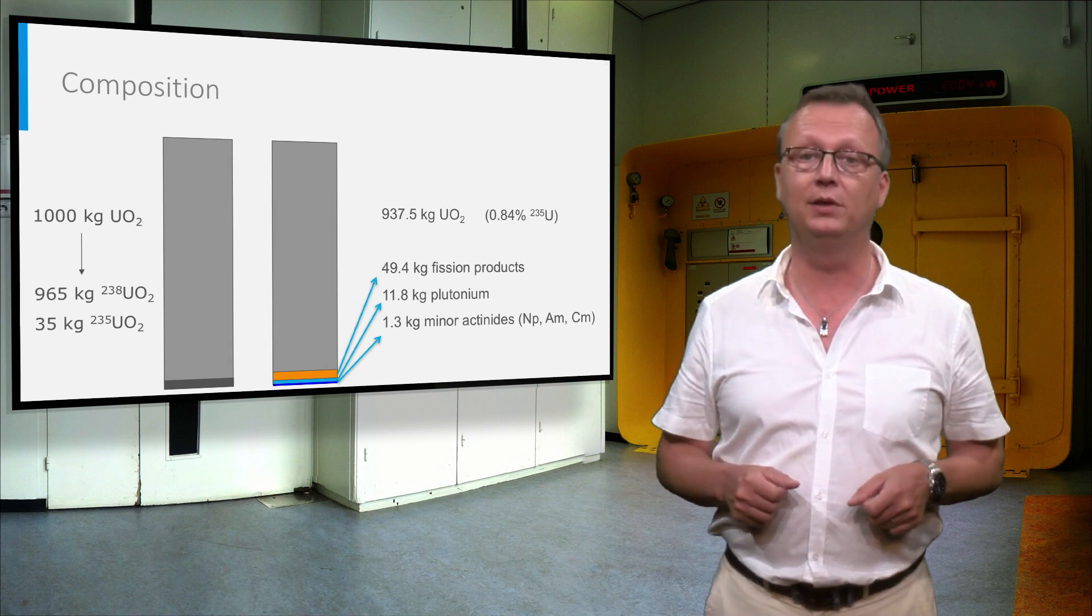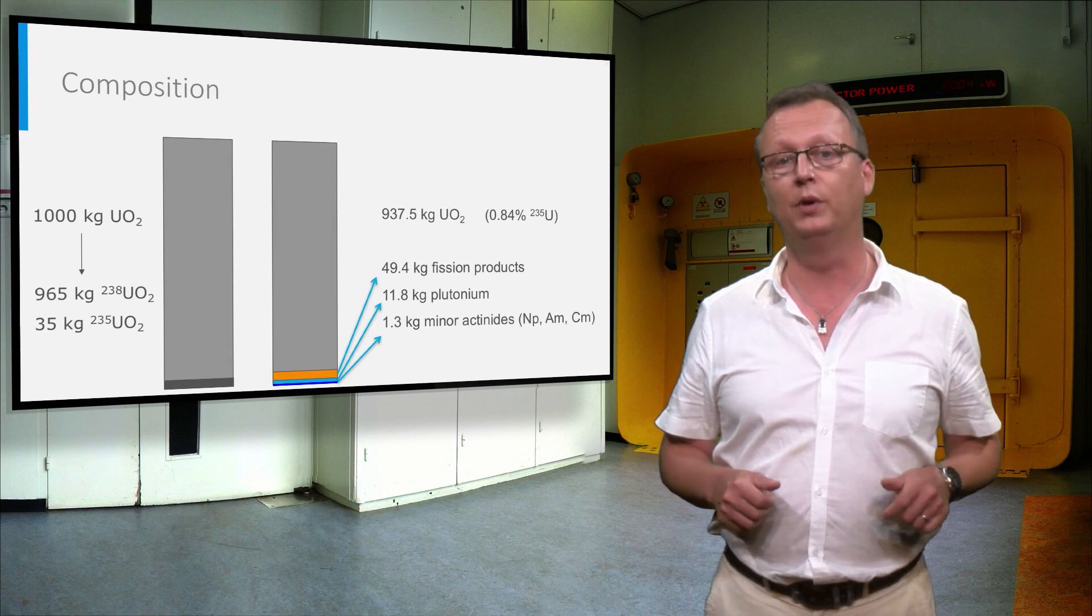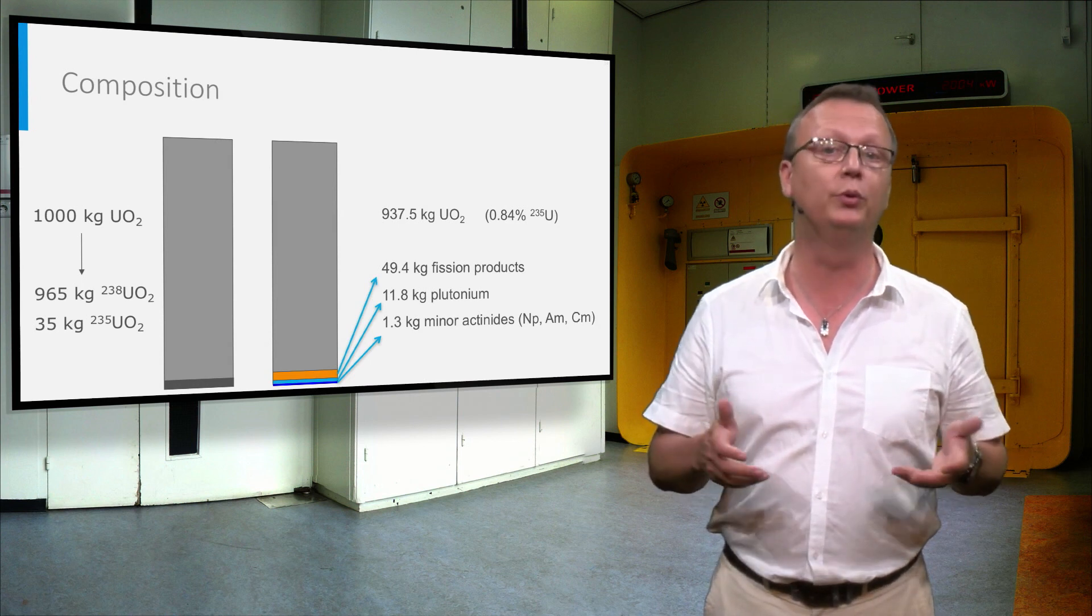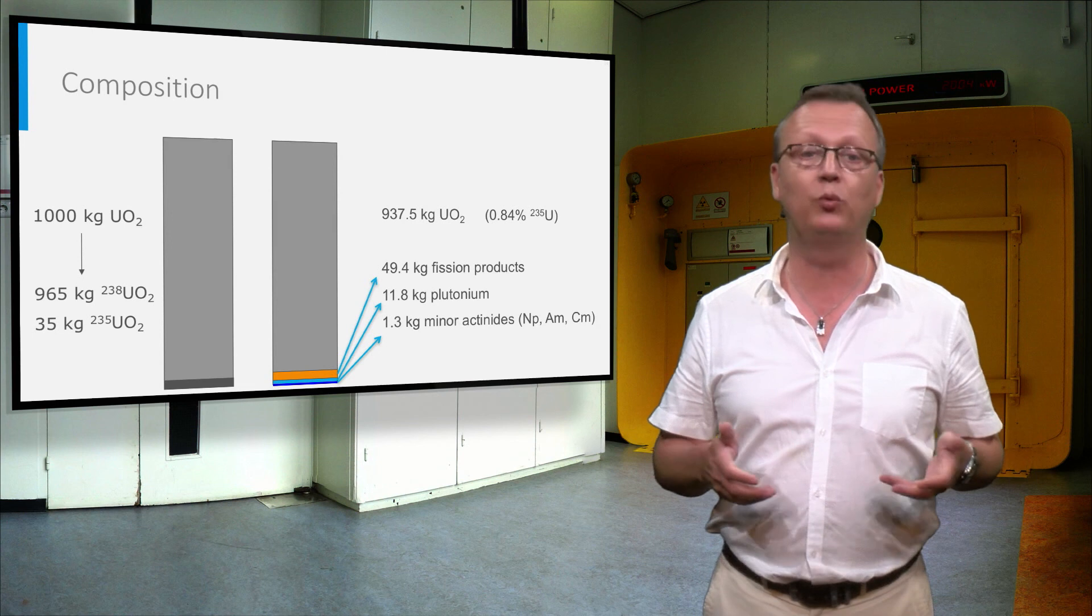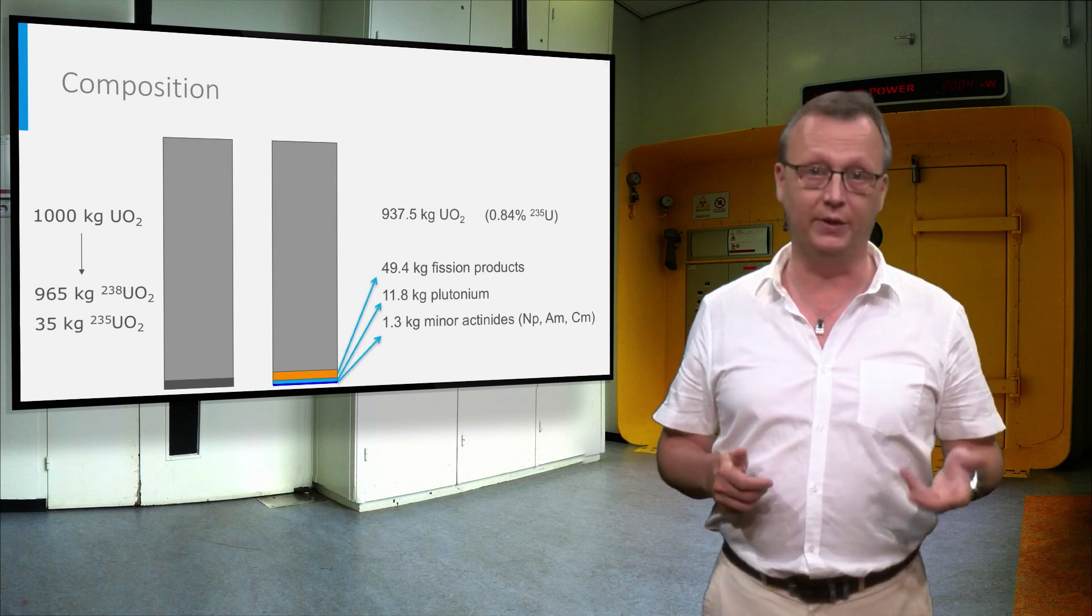So the lifetime of the fuel elements is limited to about four years, after which the composition of the fuel has changed significantly from pure UO2 to about a material with about 6-8% newly formed elements, fission products and activation products.